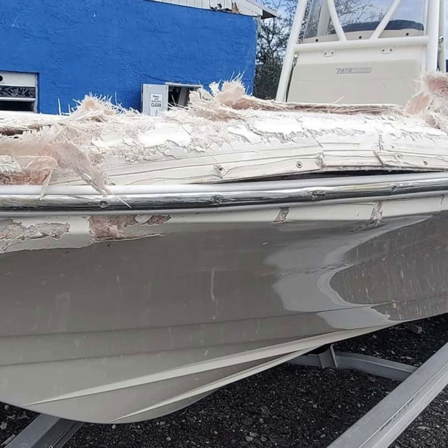So in that circumstance, when you grind your glass out, you now have a dished out area that is below grade. However much material you remove, let's say you grind out an 1/8 inch of fiberglass to get all of the damaged fiberglass gone, well, now you know that you need to apply an 1/8 inch of fiberglass to replace it. There's no sense in applying a 1/4 inch of fiberglass over that, because you're going to have to grind an 1/8 inch of it back off, because the end goal for your repair is to be back at the grade that you started at. Makes sense. Keeping in mind that you're going to end up back at grade.